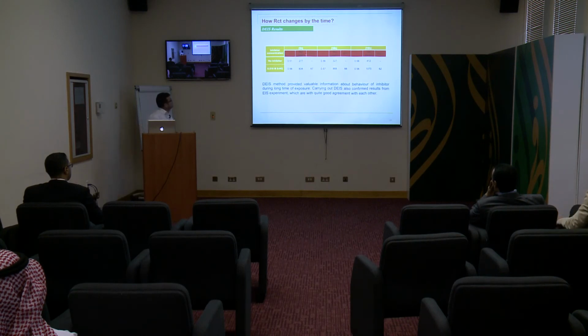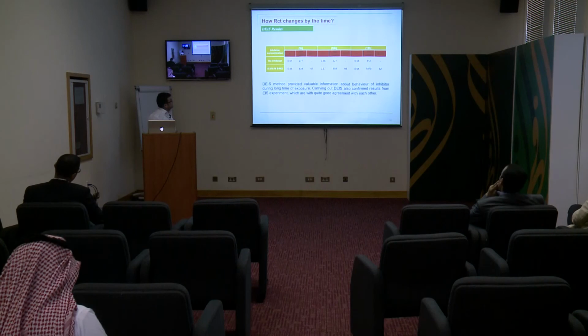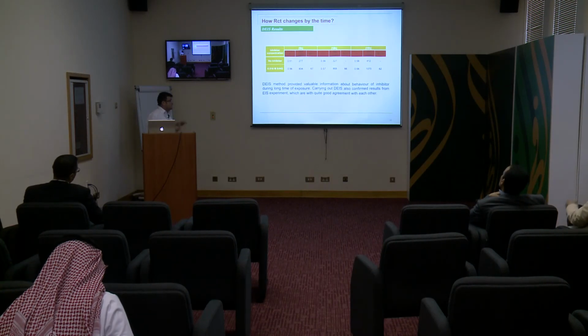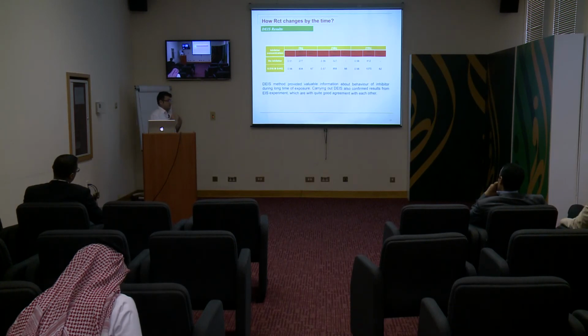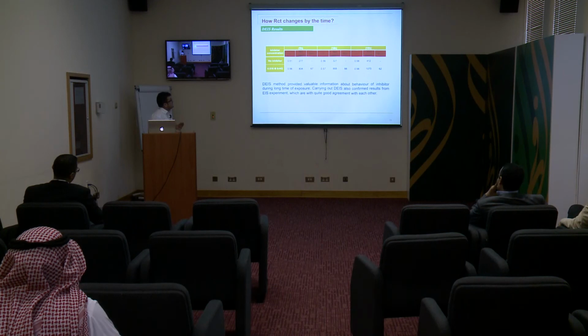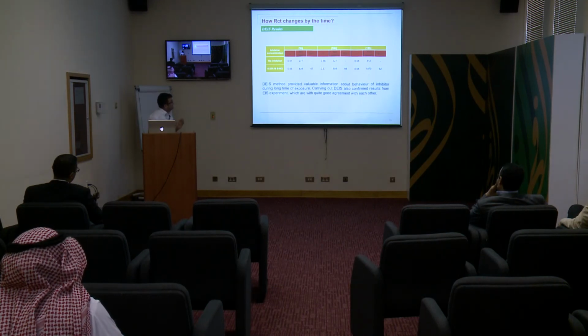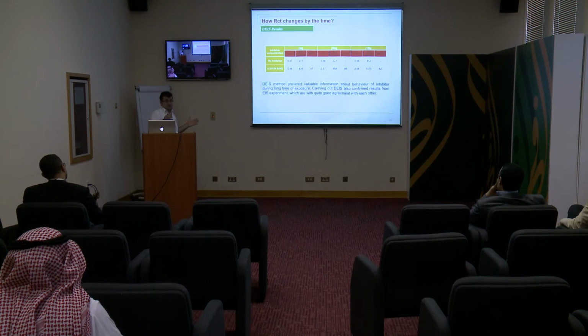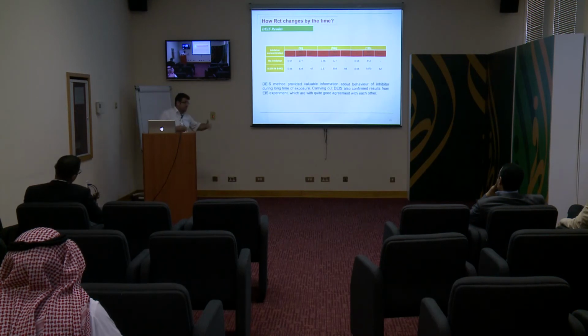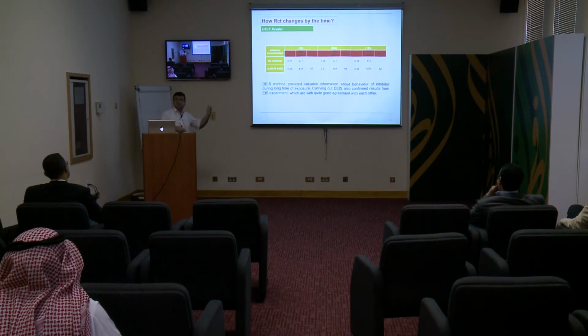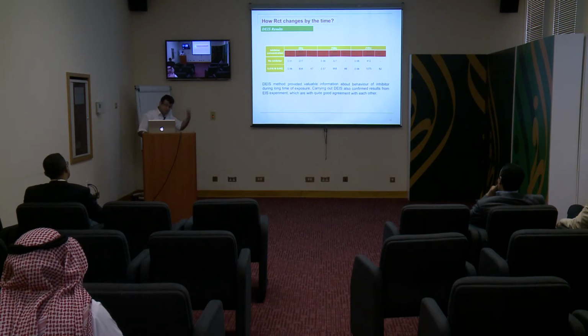So the advantage of this is you can take knowledge every time. Other methods, you just perform and you take data. But with dynamic electrochemical impedance, for example, you can take 5 hours, 10 hours, 15 hours, and see what changes. You can see when the inhibitor will lose its efficiency and when you have to add inhibitor again. In factories, in cooling systems they are using inhibitors, and they don't know when they will add inhibitor again. But with this system, when the inhibitor loses its efficiency, the lamp starts burning, so you have to add inhibitor.